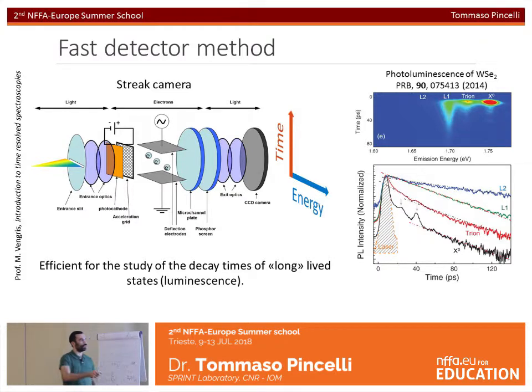And as an example, I wanted to show the photoluminescence of tungsten diselenide, which is a semiconductor that has a complex landscape of conduction band valleys. So when you excite it with a pulse of light, you create a number of different excitons in the material. And these excitons have different decay times depending on their characteristics and symmetry. As you can see, the neutral direct exciton decays the fastest, and it's actually below the limit of detection of the streak camera, so it's 4 picoseconds, and you can basically just see the laser pulse. Then you have a trion, which is a charged exciton that decays on 2 different time scales, a longer time scale, and then you have localized excitons that take the longest times.